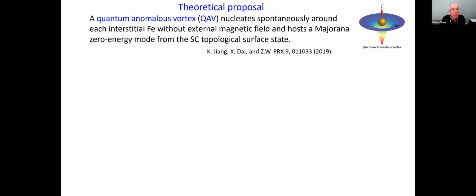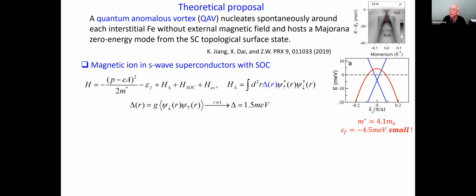So now our proposal is what I described in the very beginning, that there is a quantum anomalous vortex, a vortex in zero magnetic field that nucleates spontaneously around the interstitial magnetic ion without external magnetic field. And that hosts a Majorana zero mode from the superconducting topological surface state. So we need to, of course, do a calculation to show that indeed, in this case, it's better to have a vortex instead of a vortex-free Yu-Shiba-Rusinov state. And that I won't have time to describe in detail, but I can show you.